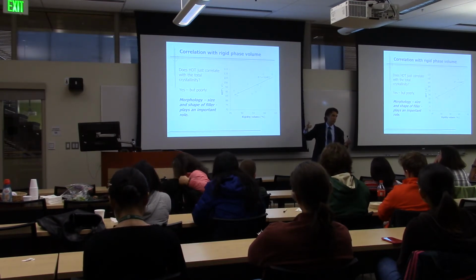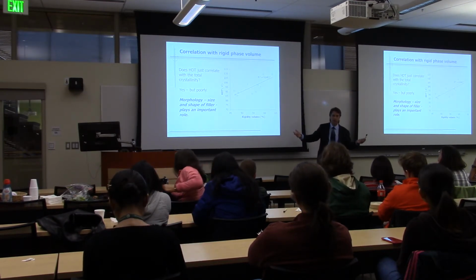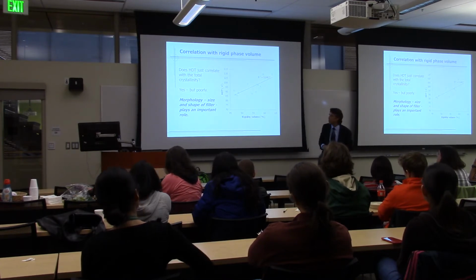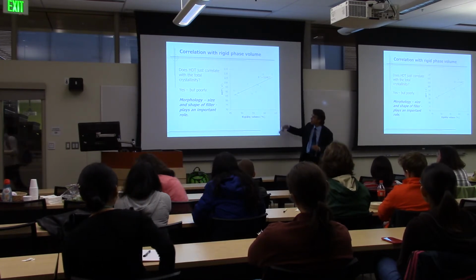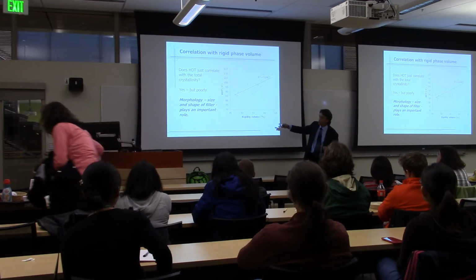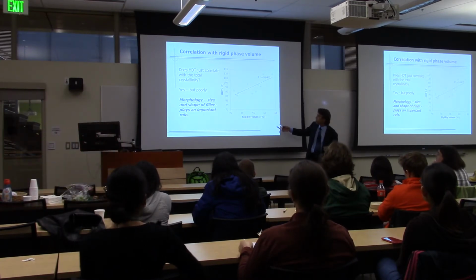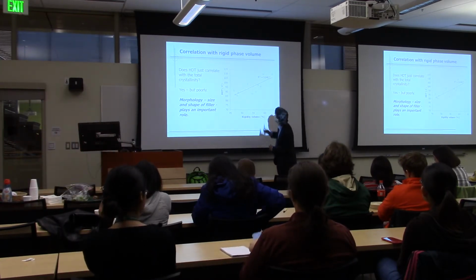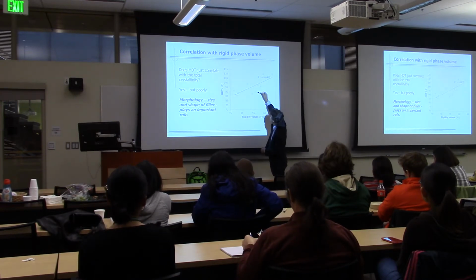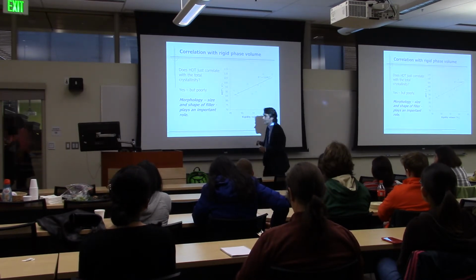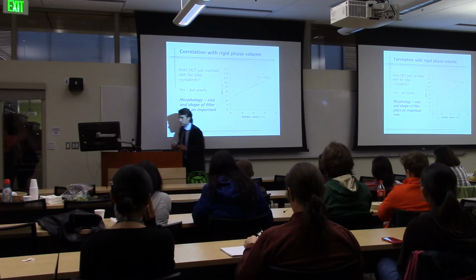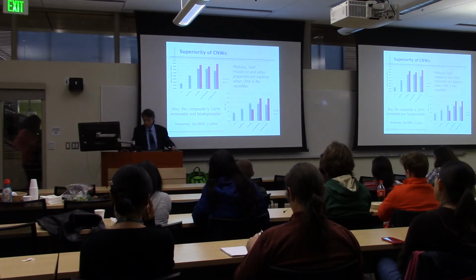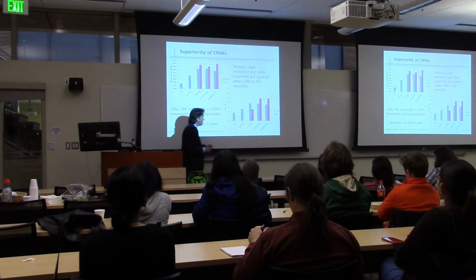Is it just the rigid volume fraction that dictates the heat distortion temperature? Here are different types of fillers, and the idea is, it does correlate with that. There's no doubt about it. But the correlation is fairly poor. If you look at the spread here, you can have maybe from 90 degrees to 110 degrees at roughly the same filler. And so it turns out that the morphology of the filler itself is very important.